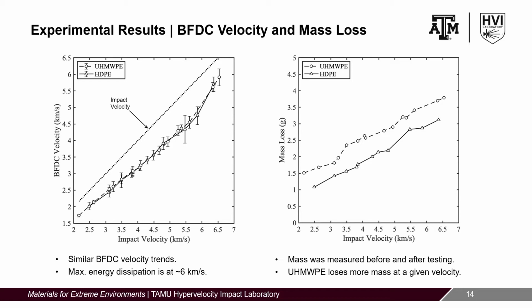Due to the finite pixel size in the high-speed images and the short time scales of the hypervelocity impact events, systematic tracking errors were introduced into the measurements and are displayed via the error bars on the plot. Interestingly, although the hypervelocity impact response of the two materials differ qualitatively, the polyethylenes have nearly the same backface debris cloud velocities for the velocity regime tested.